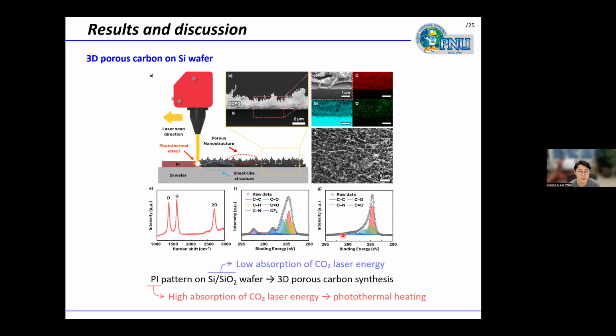So as I mentioned, the key point of this process is using the CO2 laser in this system. And also, we checked the cross-sectional image of 3D porous graphene as shown here using SEM. This 3D porous graphene is tightly attached, meaning bonded with the silicon without a gap between them. It also shows the porous structure like a conventional LIG system, and the Raman and XPS results also show that even though we're using the photo-patterned polyimide film and forming the LIG on the silicon oxide wafer, the overall characteristic is similar to the conventional LIG material.